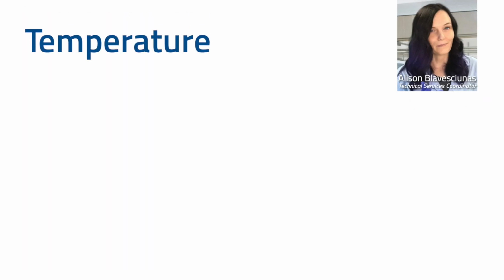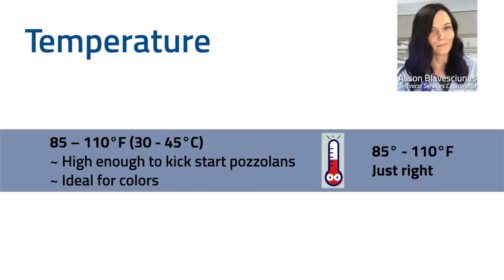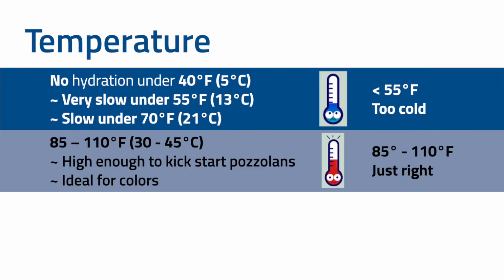Over the last 100 years or so, the industry has learned that there is a sweet spot for curing temperatures, which is 85 degrees to 110 degrees Fahrenheit. At this temperature, curing will occur within a workable and predictable time frame. If the units are cured at less than 85 degrees Fahrenheit, times start to extend. If temperatures fall less than 55 degrees Fahrenheit, then things really start to slow down, and units are likely to be too fragile to handle even after 7 days.